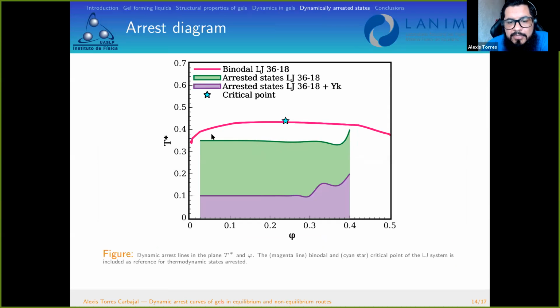Above this line for the pure Lennard-Jones system, we found ergodic states. That means states that are not dynamically arrested. And below this line, we found the arrested states. Also, in the case of the Lennard-Jones with the Yukawa tail, we found the same states, but at lower temperature. So let me stop here.